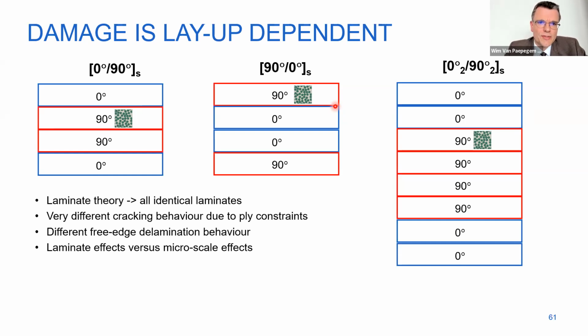Honestly, to what extent industry is already including this, I have rather the impression that as an academic, we have the role to, for example, compare different layups. And of course, now I only show two orientations, but if you have a complex layup with tens of layers, we can in an analytical way very fast give a recommendation which order, which sequence of these different angles gives lower or higher interlaminar stresses, just elastically.